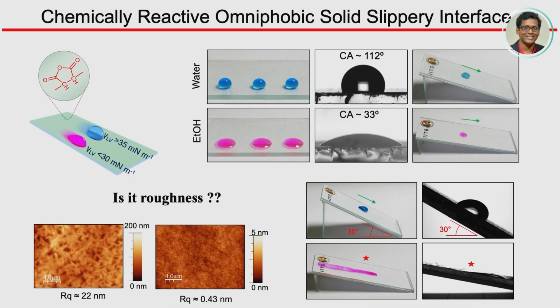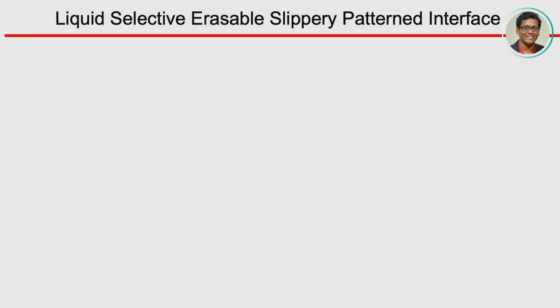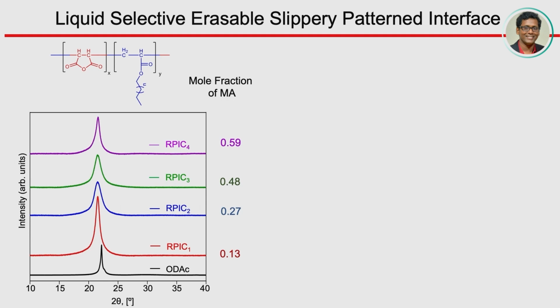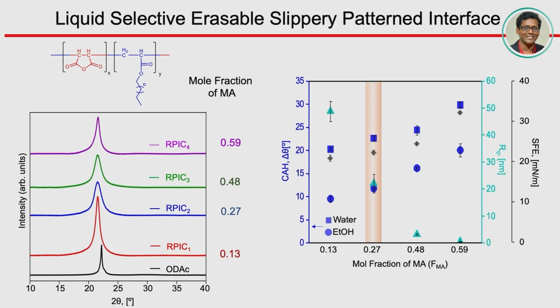So it is not roughness, it is something else. What is that? So we found that when we gradually vary the molar composition of this maleic anhydride, crystallinity is there because this part is still there quite weight to make the crystalline domain, but probably the crystalline domain size is varying, and that contributes to changing this roughness. As you can see, roughness is gradually decreasing. Okay, this is the roughness domain, and you can see it gradually decreasing with increasing the molar fractions of this maleic